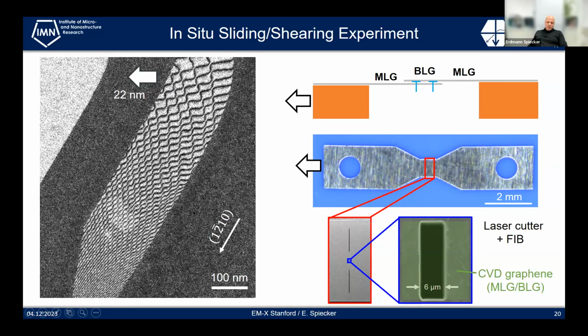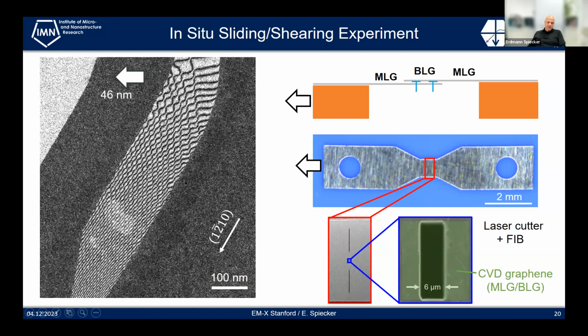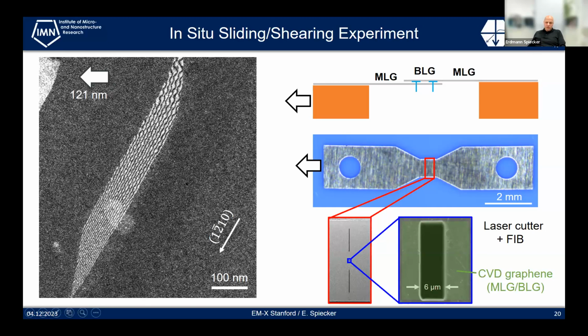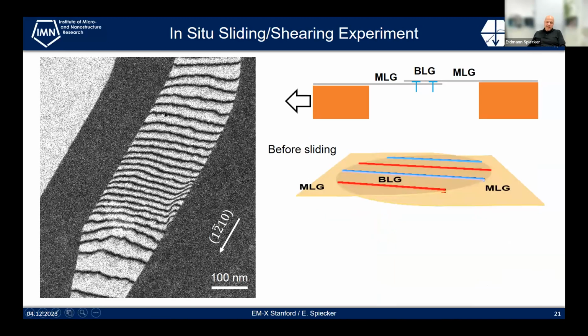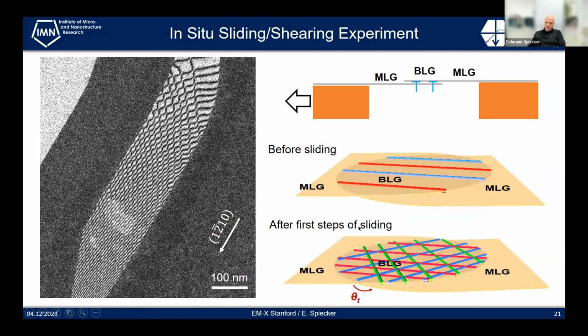Okay, now of course we see that a dislocation network evolved, but we want to learn more about the process. We think that twisting sets in, but we have to prove that, and for that we have to make a Burgers vector analysis. And this is shown now on the next slides. So here's a summary again. In the beginning we have some arbitrary dislocations with different Burgers vectors, but after first steps of sliding, a network evolves, and this network is made of, as we will see in a second, screw dislocations.